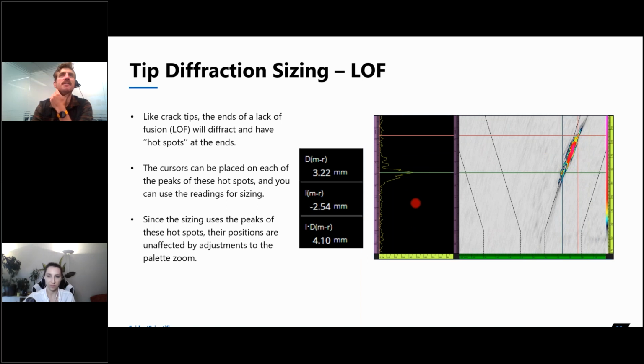Again, coming to the lack of fusion that I had an image of earlier, same idea, but we basically have to do the hotspots for our tip diffraction on both ends. So we find the maximum in our A-scan here, the maximum in our A-scan here, reference cursor, measurement cursor, and the same thing using our readings. We know that it's 3.2 millimeters high, and the index direction width is 2.5 millimeters as well. And the total length of our lack of fusion is going to be 4.1 millimeters. The actual operation in order to do this is going to be maybe 3-4 clicks, and we know already the exact size of our lack of fusion, versus if we were to do this in an amplitude-based technique, it would be significantly more than 3 or 4 clicks.